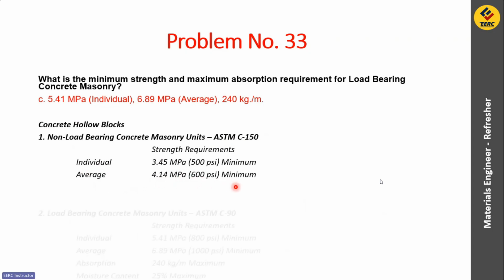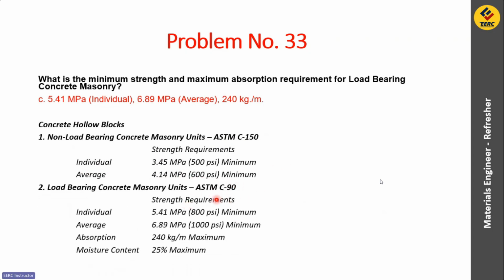And then for the load-bearing naman, under ASTM C90, strength requirements for individual is 5.41 megapascals or 800 psi minimum. Average is 6.89 megapascals or 1000 psi minimum. Absorption value of 240 kilograms per meter cubic maximum, and moisture content of 25% maximum. Okay, so this is for non-load-bearing concrete masonry units under ASTM C129 and load-bearing concrete masonry units under ASTM C90. Okay, so madalas din ito tinatanong sa class, so please take note.